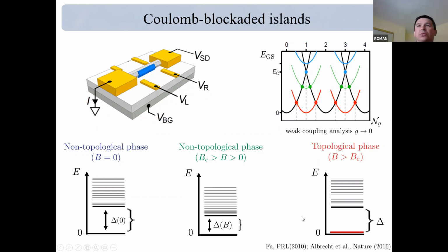So this is the picture that we are looking for. If we have some small deviation, a small splitting energy in the ground state, then the positions of the peaks for the odd state and even state will be shifted relative to each other by this small tiny amount. And by looking at the scaling of this small tiny splitting as a function of the length of the wire, one is essentially probing a non-local property of the system. One is probing how the ground state degeneracy is lifted as a function of the length of the wire.